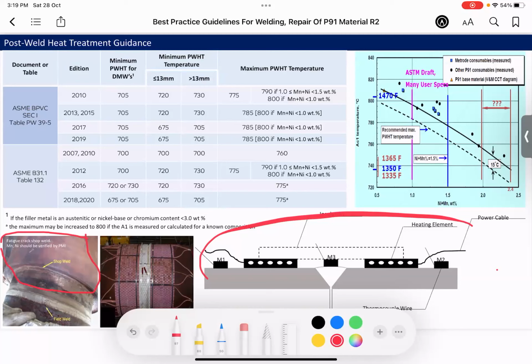So we should always verify the content of nickel and manganese prior to welding. So the PWHT procedure should be reviewed carefully. This temperature, AC1 temperature, should be calculated for a known composition. And the chart on the right side shows how the AC1 temperature can change with a different composition, as a function of nickel and manganese content in the steel.